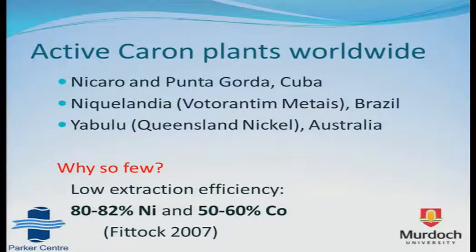Currently, there are not many Caron plants active. There are two in Cuba, in Brazil there is one, and then in Australia there's the Yabulu Queensland Nickel Refinery. The reason why there are so few is possibly related to the low extraction efficiency of the process compared to other techniques, with only 80 to 82% of nickel being achieved at the Yabulu plant, and cobalt even lower, with an extraction efficiency of 50 to 60%. So there's a significant problem which is causing this low popularity of this process.